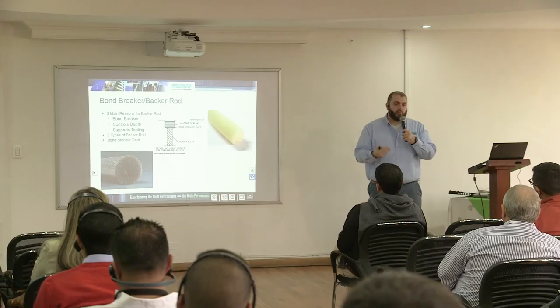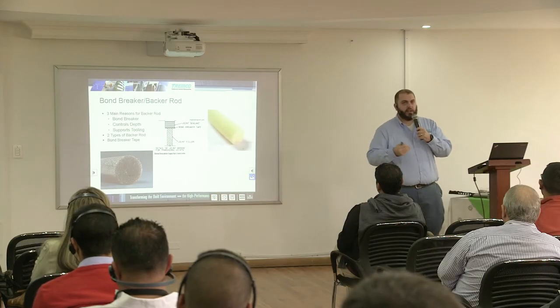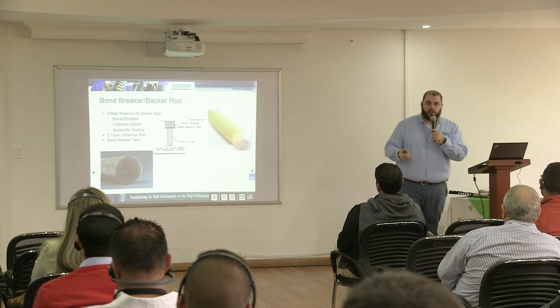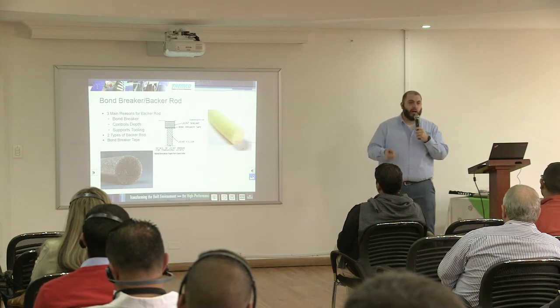A closed cell backer rod is, what's the word I want to use? It's impermeable. It doesn't allow moisture to get to the other side of the joint. So if you have a horizontal joint on grade, you'd want to use a closed cell backer rod. And the closed cell backer rod, like I said, keeps moisture from getting to the backside of the sealant. If you have moisture getting to the backside of certain types of sealants, you could have some issues. You could have what we call outgassing.